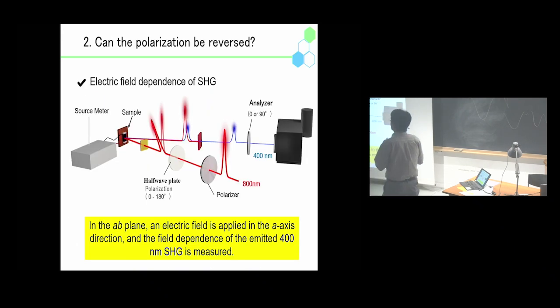Okay, so let's go on to the second part. In the second part, we checked the existence of the polarization of this system. The next problem is whether the polarization can be reversed or not. That is a quite important problem in ferroelectrics. But unfortunately, this lutetium Fe2O4 is a little bit conductive, so we can't use the conventional measurement system for the usual ferroelectric materials, such as the P loop measurement. So we considered, based on SHG measurements, measuring such a polarization reversal.